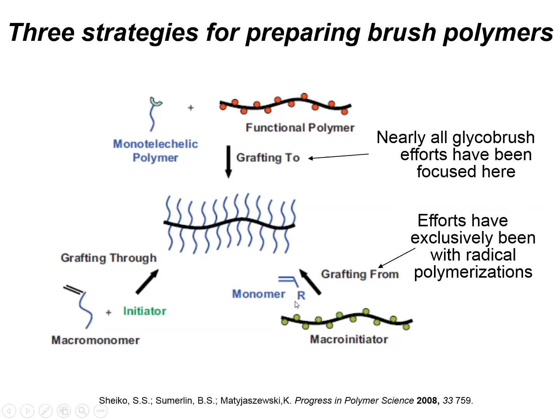And so you get a hydrocarbon backbone, hydrocarbon-based side chains. And for us, that's not so appealing because we cannot get the peptide backbone conformation that you would see in a natural mucin. They wouldn't be biodegradable by natural proteases. The orientation and this alpha conformation in the sugar is actually quite important for the structure and also biological recognition. So we needed to develop some new chemistry to attack this problem.